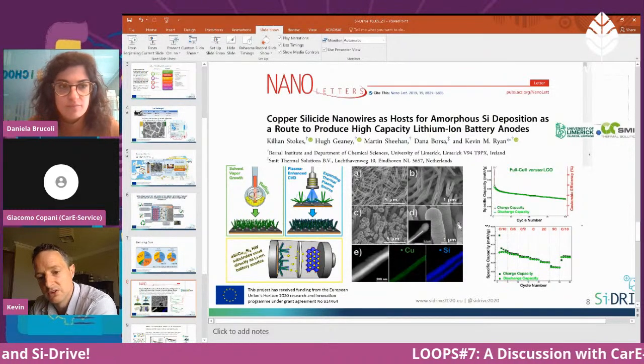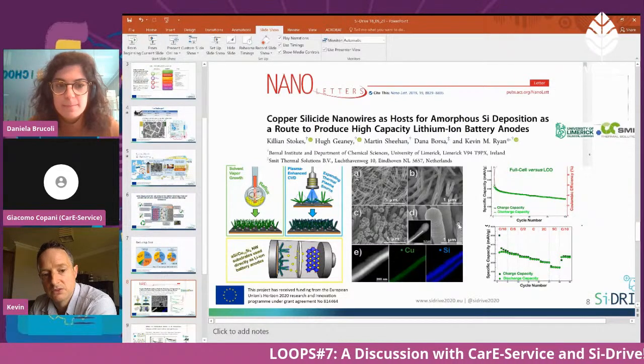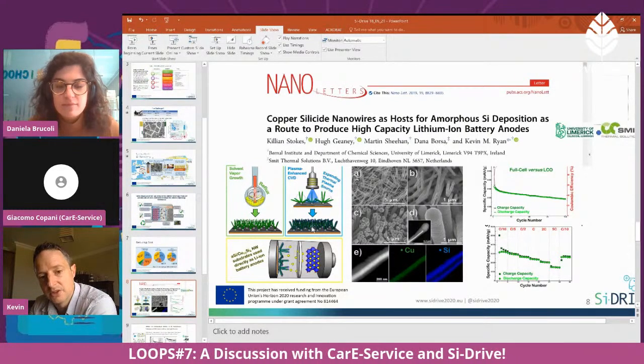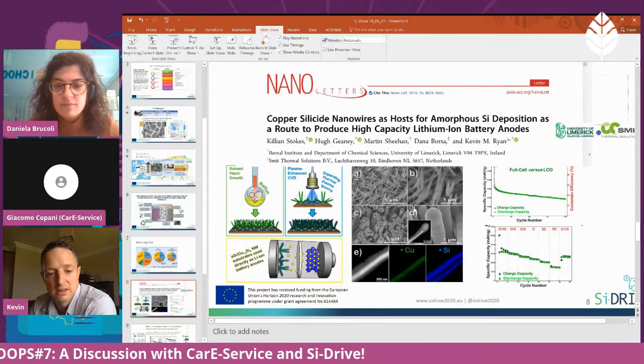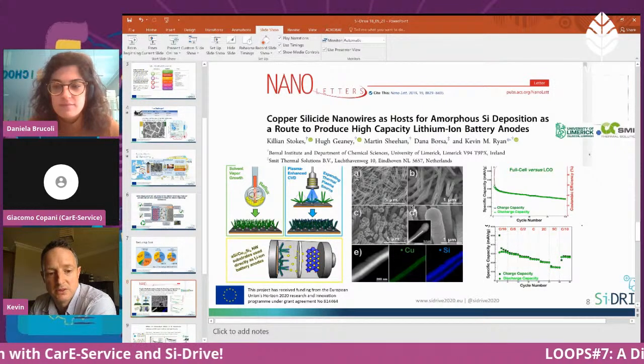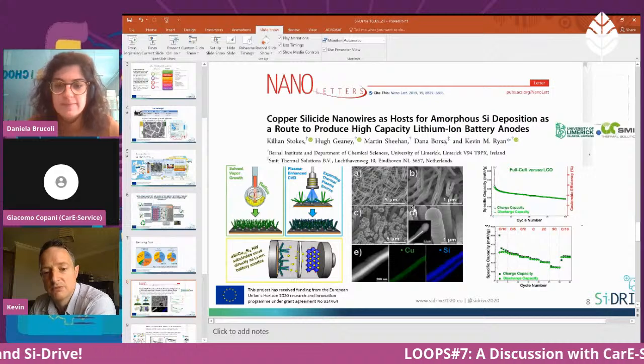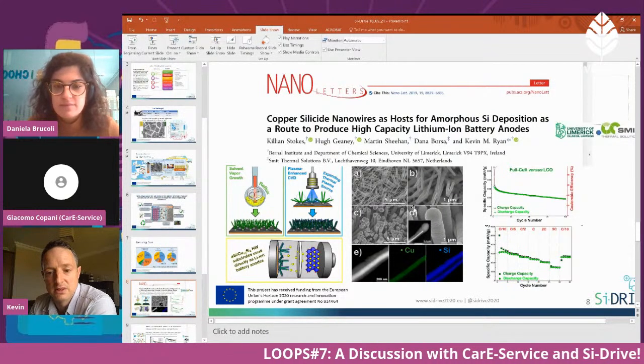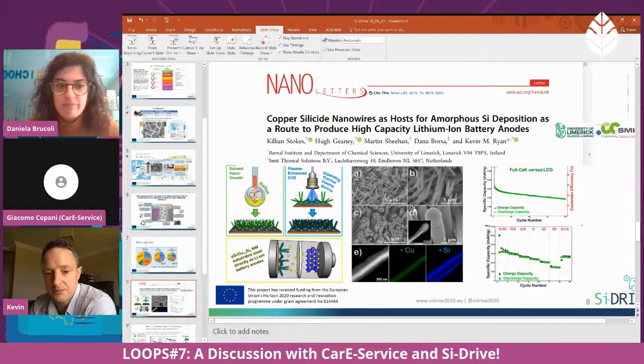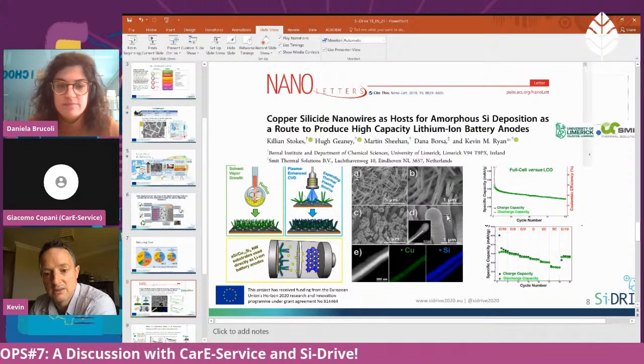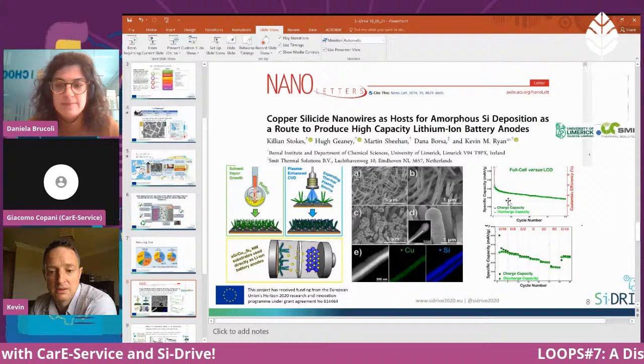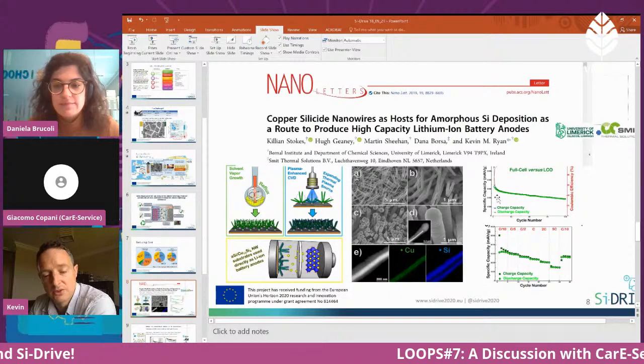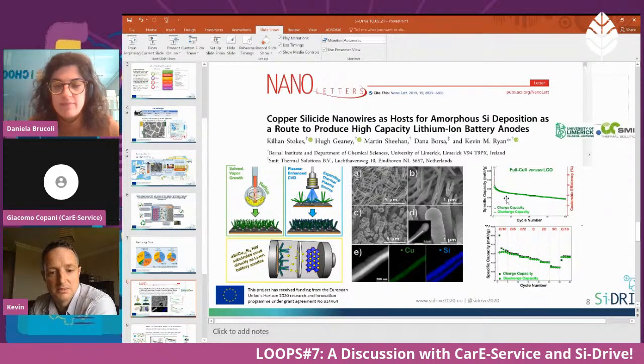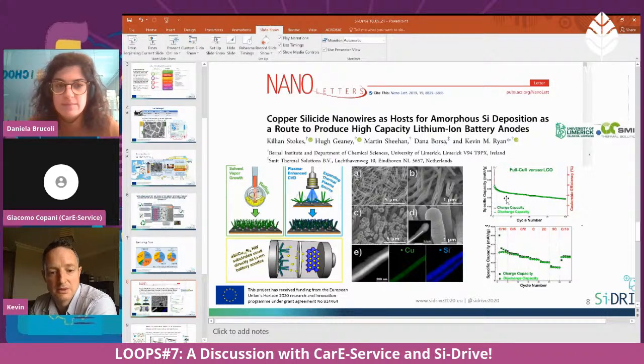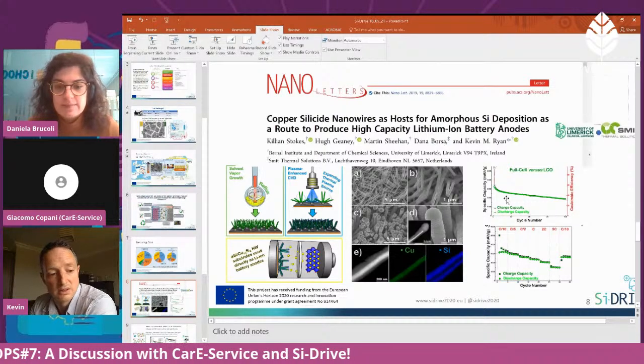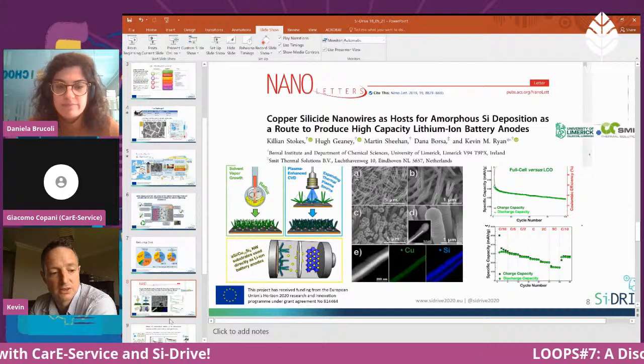And within the consortium, this is just showing one aspect. Once we have these substrates, they are sent to Siditech, who do the full cell chemistries, and they also take the cathodes from KIT and bring those together in full cell chemistries. But with these nanowire anodes, we get a very excellent rate capability, and a very high specific capacity, and we get further improvements on this by controlling different properties such as the coatings on the silicon nanowires for artificial SEI, etc.